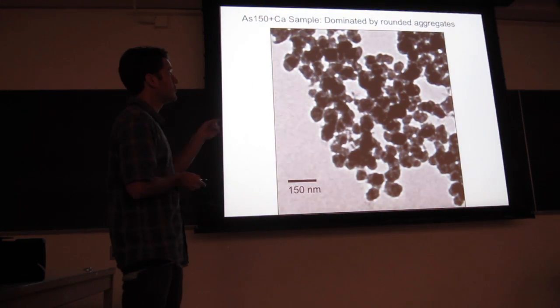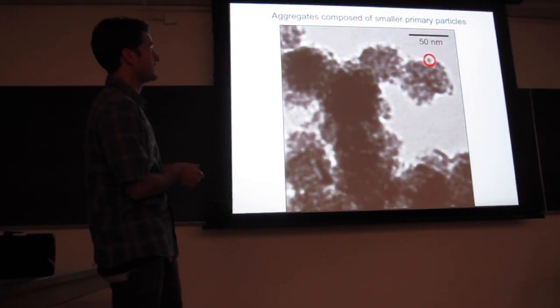So at the larger initial arsenic concentration, we see much fewer needle-like platelets, and we see a pretty homogeneous aggregate here. And we can zoom in on one of these aggregates, and we see that they're composed of primary particles that are extremely small. And again, these primary particles are going to have an extremely high surface area, and they're going to be extremely reactive.